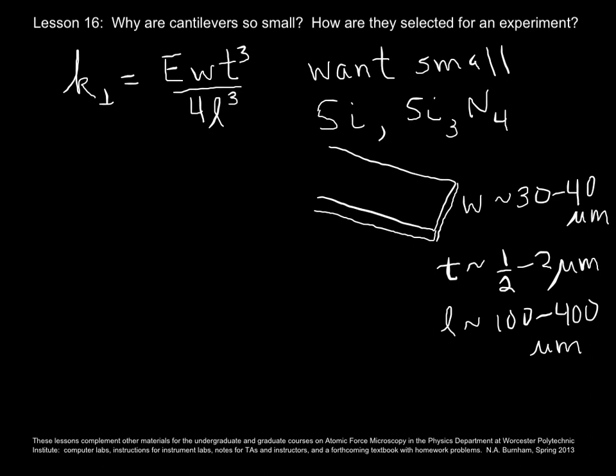If you look at the equation again, you see that the thickness is cubed, and the thickness is very small. So, indeed, the numerator is much smaller than the denominator. And in order to achieve such small thicknesses, you need to have this silicon microfabrication process. If you tried to make a cantilever yourself, I've never seen one that matches the low spring constants that you can make with a silicon microfabrication facility.